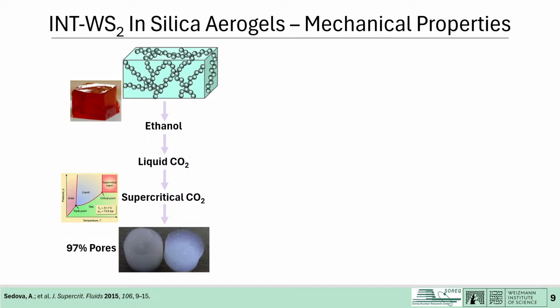Then we started working with these interesting materials, aerogels. I think they're interesting and challenging in the preparation step. It starts from a gel. It basically looks like gelatina. In the first step, when it's forming as a gel, it's already a porous material. Nonetheless, the pores are filled with liquid. So the idea is to arrive at the dry product without the pores collapsing into themselves.